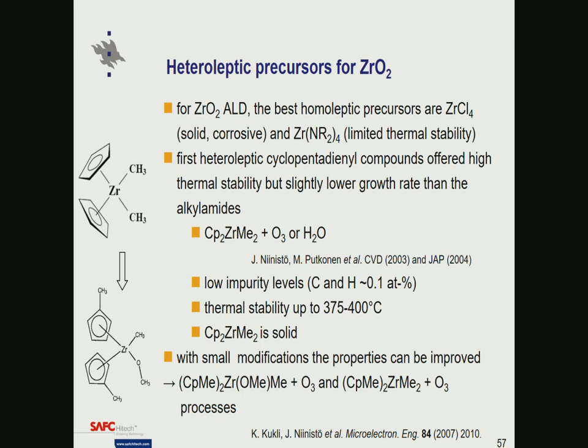There are lots of heteroleptic precursors available. I've chosen zirconium and to some extent also hafnium oxide as an example only to show how the evolution has gone there. So if looking back, for the homoleptic precursors for zirconium, basically two compounds were dominating. Zirconium tetrachloride is a solid and corrosive, which causes some concerns to many. On the other hand, there was zirconium alkylamide, which has a limited thermal stability, somewhere around 250 centigrades. Then, this was somewhere around 2005, and after that there was a look at the cyclopentadienyls. One can make homoleptic cyclopentadienyls for zirconium, but also heteroleptic. And in the first one, there were two cyclopentadienyls and two methyl ligands here. This could be used with ozone or water, producing rather pure films at higher thermal stability compared to zirconium alkylamide.